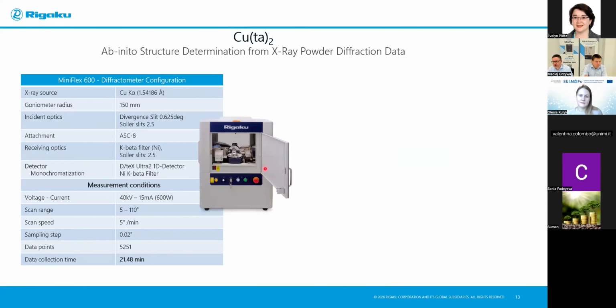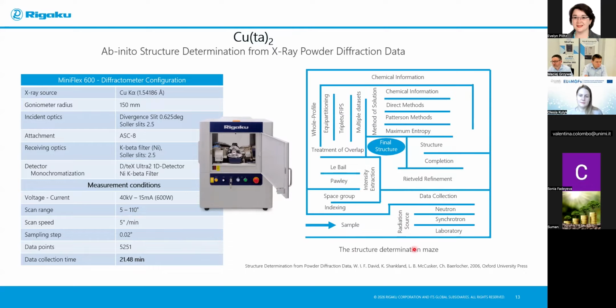Ab initio structure determination from powder data. In this case, we use the Miniflex, and the data were collected only within 22 minutes in the range of 5 to 110 degree 2 theta. On the right-hand side, you can see the typical structure determination maze, where after data collection, the next step is indexing of the powder pattern, space group determination, intensity extraction, treatment of peak overlap, getting the structure completion, and Rietveld refinement as the last step of the whole process of structure solution.